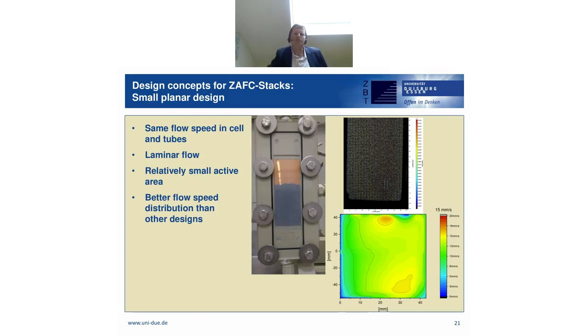Here is a planar design, which is depicted here on the left photo. Again, we have a glass plate instead of the cathode side here to study the flow behavior. The zinc slurry is coming from the bottom side. It is just moving upwards, and we see that we have the same flow speed in the cell and the tubes, and the zinc flow is quite regular and laminar, flowing over the current collector.